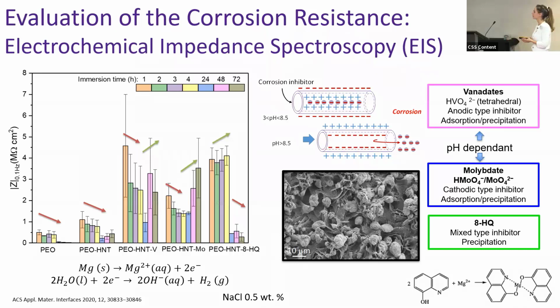So here we are representing the total impedance of my coatings at low frequencies as a function of the immersion time for all my materials. The first two columns correspond to the PEO coating and to the PEO coating containing empty nanotubes, and they both follow the same trend. We can see that the corrosion resistance decreases during the first 4 hours, and then after 24, corrosion progresses very intensively. So probably the barrier properties of my coating lasted for 4 hours. The incorporation of empty nanotubes had some effect on the overall corrosion resistance, but they didn't delay the start of corrosion phenomena